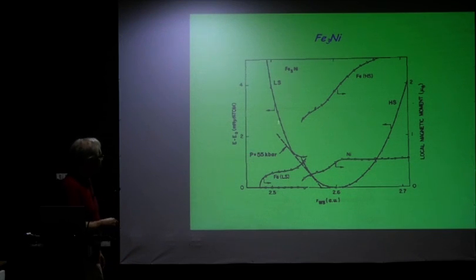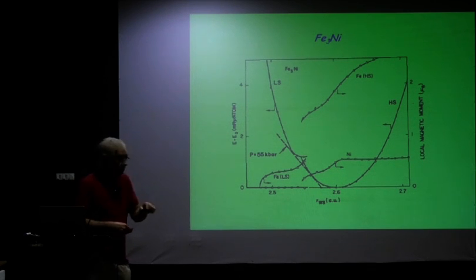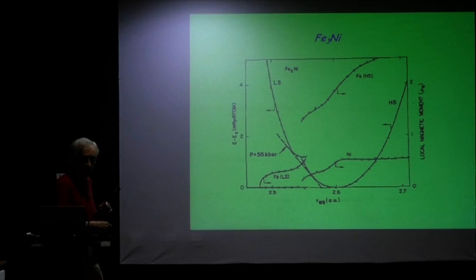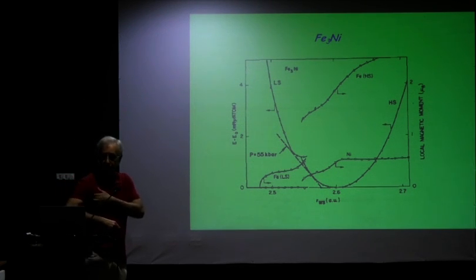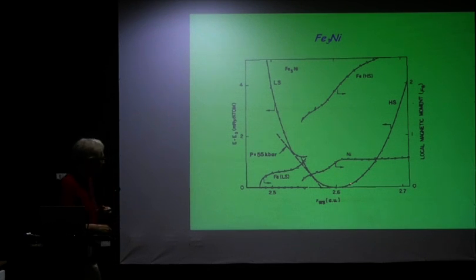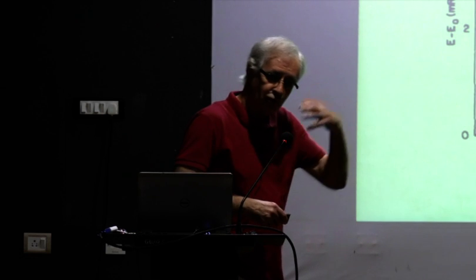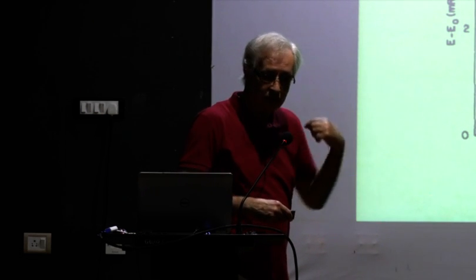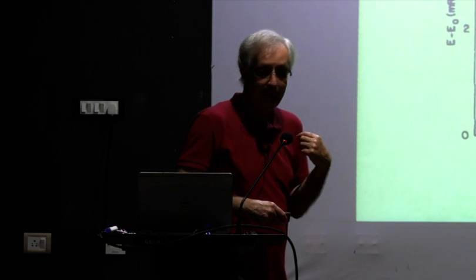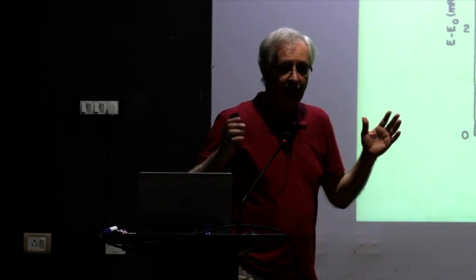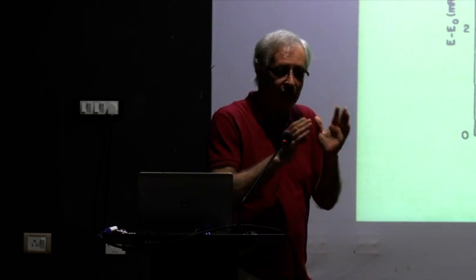In this case, you see that it is the high spin state that is of lower energy. And the low spin state, it is here. The curvature of these curves gives you the bulk modulus, the second derivative. So that if you look at this all together, you find that the anharmonicity is not towards larger volumes, but it is towards smaller volumes. Yeah? So this means that we can make this thing smaller than it should be.